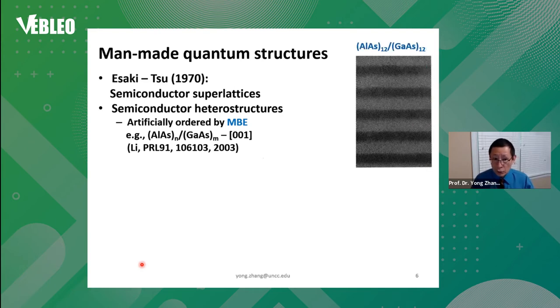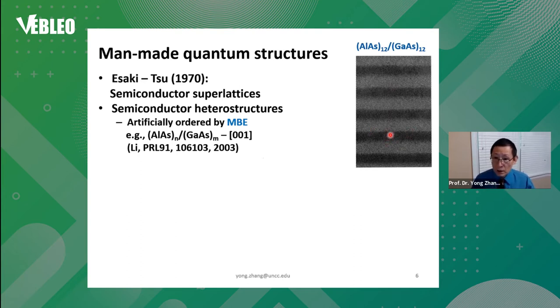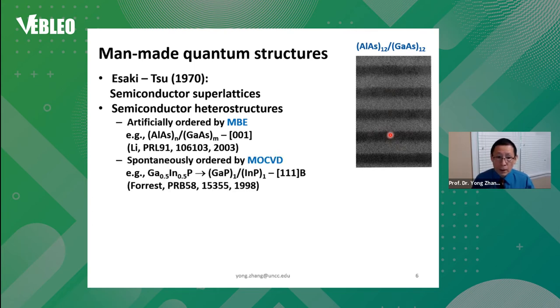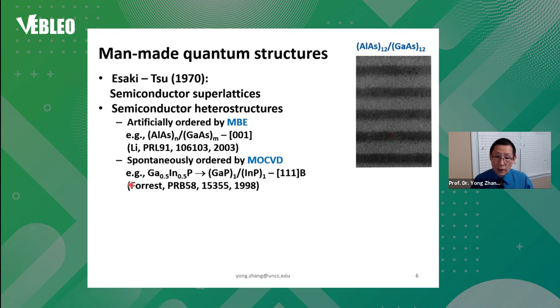The best known example is aluminum arsenide / gallium arsenide superlattices. But if you look carefully, they are not perfect — you get lots of fluctuations at the interface. So it's practically impossible to make an atomically abrupt interface with this type of approach. Another way to get a superlattice structure is by something called spontaneous ordering, which often occurs in MOCVD growth.